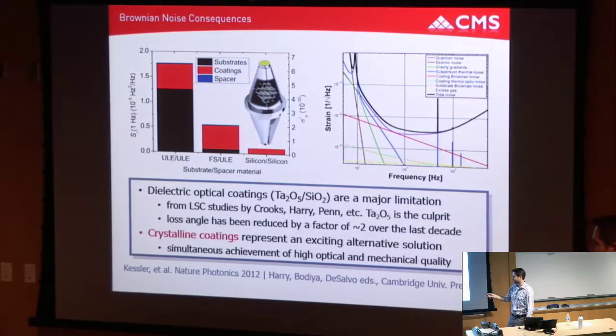And now you're basically left with the coating noise dominating the noise of the system. To put it in perspective, the Q of this bulk silicon can be billion level. The mechanical quality factor of the coating is something like a few thousand, 2,000, 3,000, 5,000, something like that. So there's a huge discrepancy in mechanical losses in those systems. So really the last frontier is to reduce the mechanical loss in the coating. This plot is totally unreadable. I need to one day figure out a way to make this readable, but I'll walk you through it.